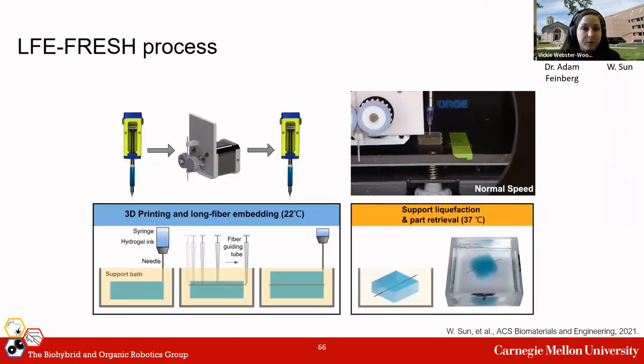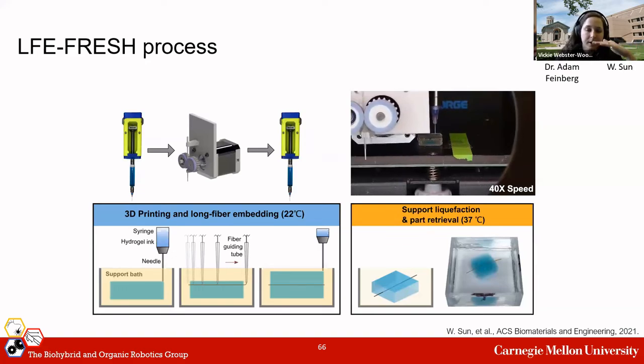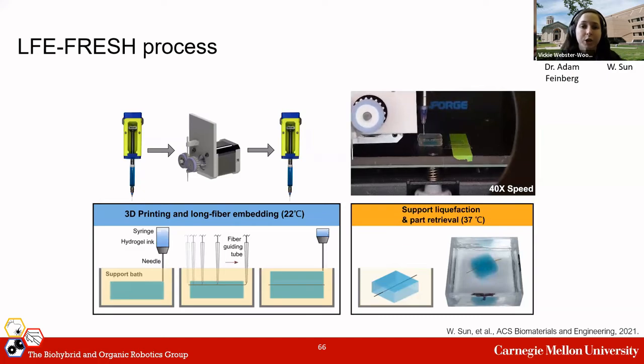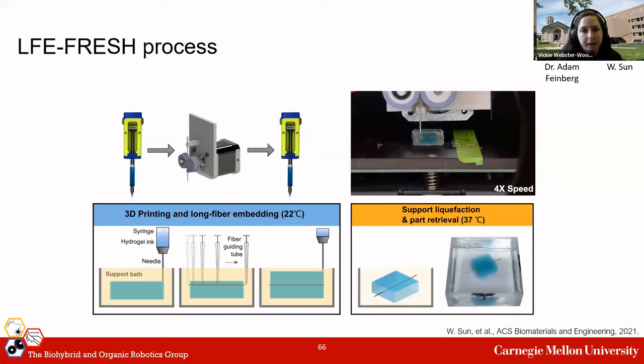In our LFE FRESH process, or long fiber embedding FRESH process, we begin by printing the primary hydrogel into the support bath. And then fibers can be embedded either layer by layer or embedded directly in 3D within the hydrogel. And we can go back and print additional hydrogel as needed to encapsulate the fibers. After we're done printing, we can then liquefy the support bath for part retrieval.